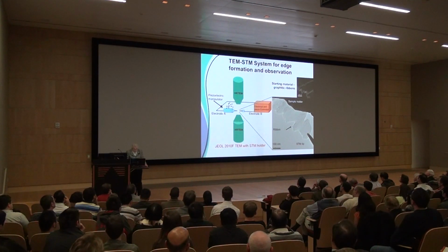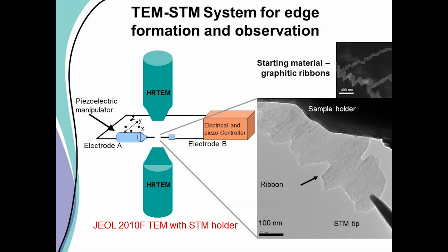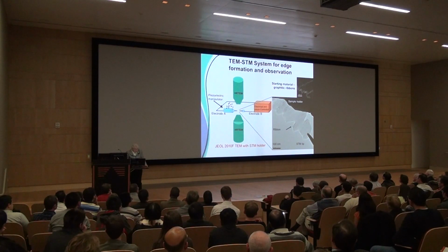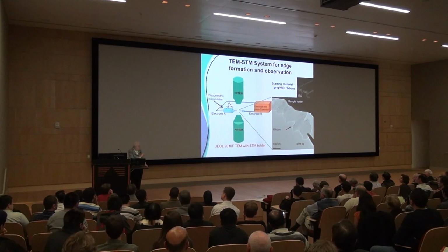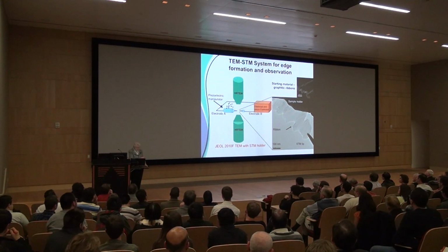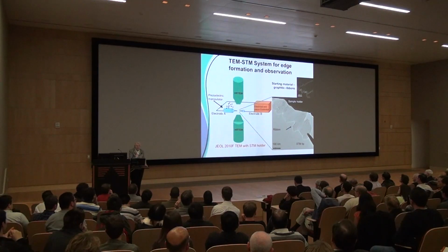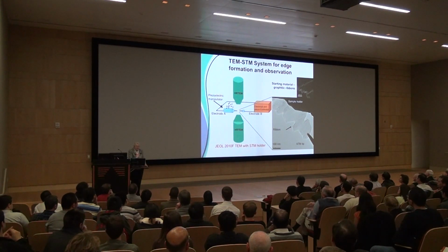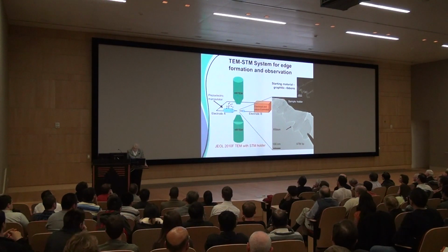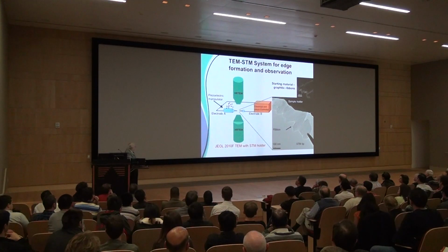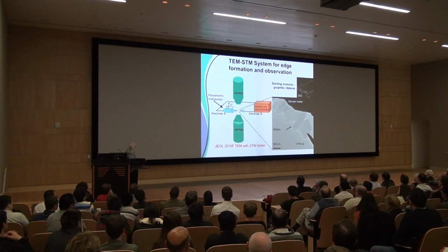And now I'm going to show you finally what we do with these edges to make them beautiful. This is another student's thesis. We asked ourselves, suppose we did the transport measurement inside a microscope. TEM microscopes allow you to put little gadgets inside. So we have a very simple gadget, as shown here, that will measure transport, to measure IV characteristics. It doesn't measure too much, but IV characteristics it does. Then we could put 2 electrodes. So we have an STM chip here, and then we have a sample holder. So this is ground, and this is voltage.